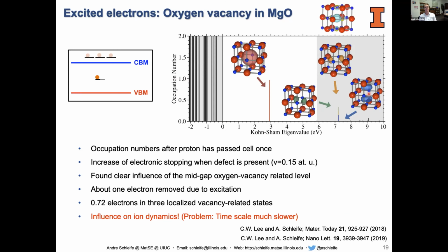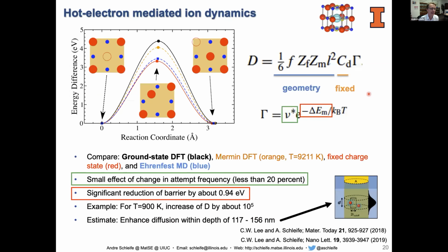The lifetime of the defect is long in magnesium oxide, on the order of nanoseconds experimentally. We unfortunately can currently not predict it. But what we then did is we looked at the diffusion barrier of this oxygen vacancy for different situations of the electronic system. So the black curve is the ground state.